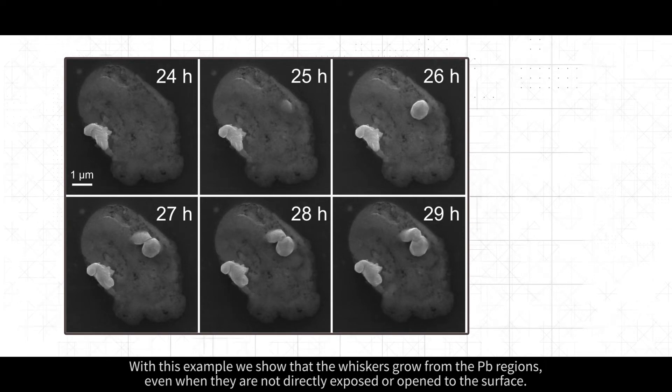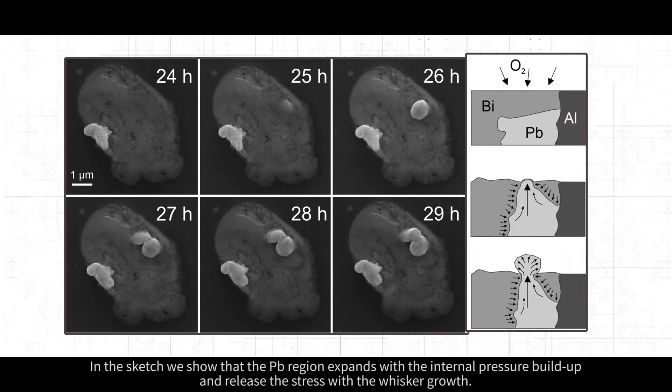With this example, we show that the whiskers grow from the lead regions, even when they are not directly exposed or open to the surface. In the sketch, we show that the lead region expands with the internal pressure buildup and releases the stress with the whisker growth.